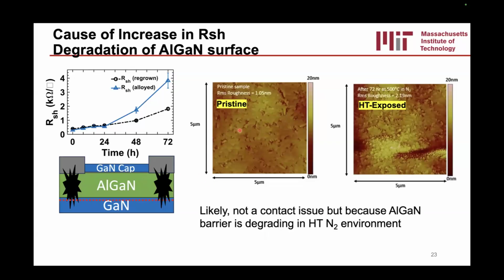And so we did some AFM measurements of a pristine sample. And the same sample, we looked at the same area after the high temperature exposure. And you can see here that the surface morphology has significantly changed after the full high temperature exposure. The roughness has increased from 1 nanometer to 2.2 nanometers, and the topology has significantly changed. And so it's not really a contact issue, but it's a fact that the AlGaN barrier is degrading, and that's making the contact measurement very difficult.